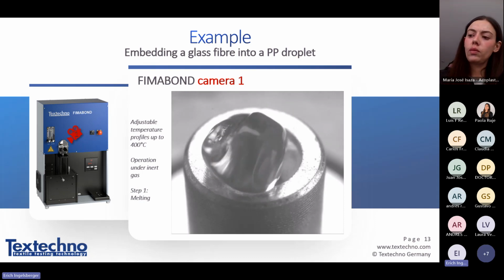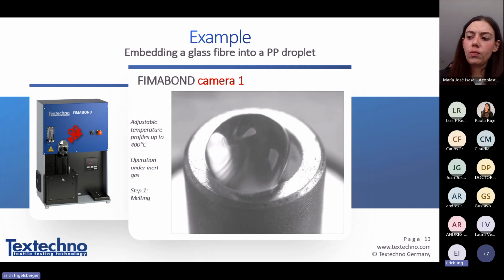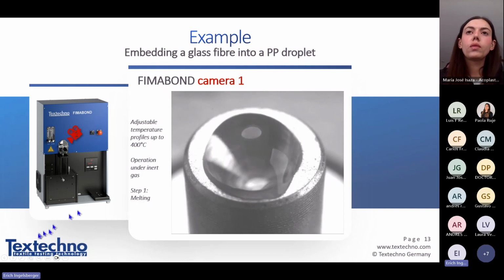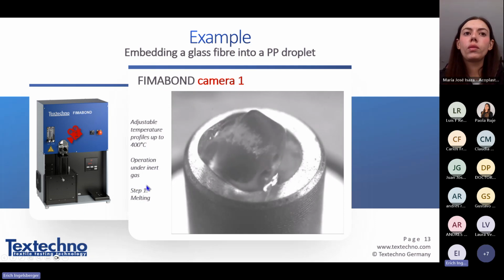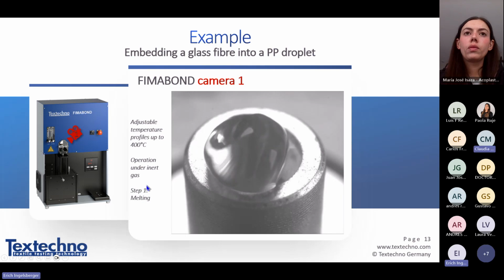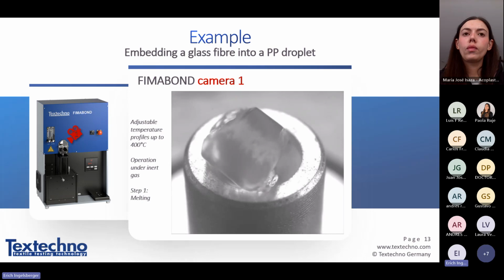And when the drop is melted, which of course can also happen under inert gas - for polypropylene not required - but to prevent oxidation of the matrix, we can use an inert gas flow inside the preparation zone.